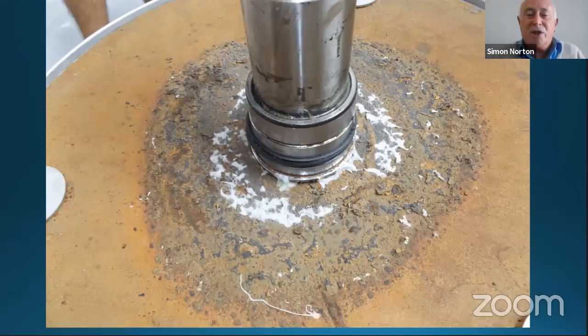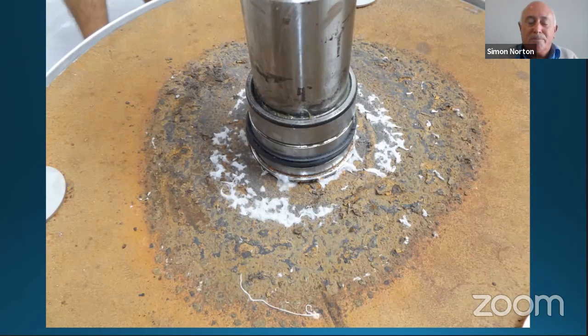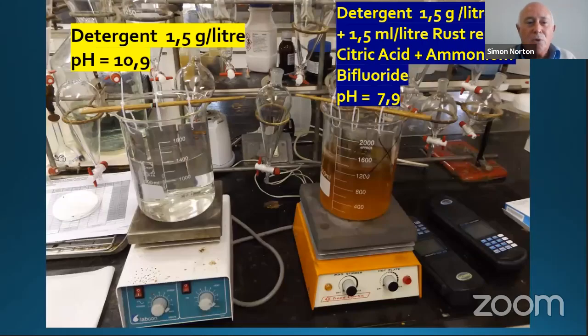When they had to get rid of the staining on the sheets, the pillow slips, and the towels, they used a special form of stain remover, a material that contained very, very corrosive halogenated material, fluorides, which are as problematic to stainless steel as chlorides. And what we did was, in the left-hand beaker, we put test plates in a solution made up with just the detergent. And on the right-hand one, we made a solution with the detergent plus this so-called rust remover or stain remover. We then put them on magnetic stirrers. We turned the temperature up as if it was in the washing machine, and then we left it running for the night.